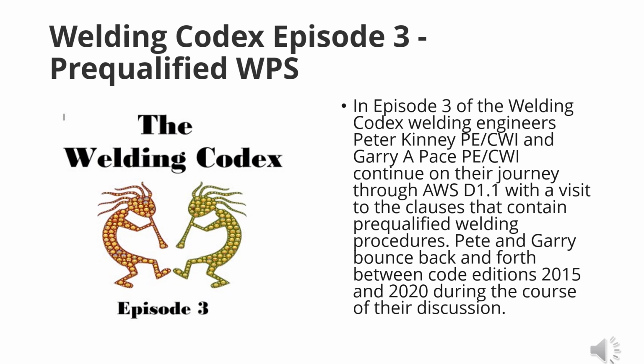Correct. They're pretty robust. It's not where we have to really look at doing post-weld heat treatment to drop hardness, or post-weld heat treat bakeouts to make sure our hydrogen gets driven out, or that we really got to look at using extremely low hydrogen materials, or we don't have to worry about hardness constraints by cooling rate from the welding process. Running within the guidelines of pre-qualification has basically already taken care of those issues.